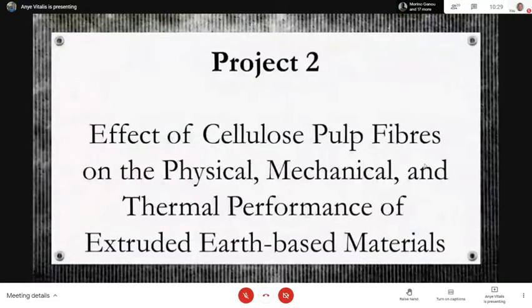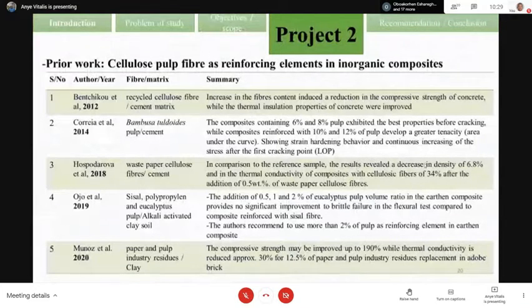Project 2 consists of the effect of cellulose pulp fiber on the physical, mechanical, and thermal performance of earth-based material. So now, what previous work has been done using earth-based material? We have Bentchikou et al. who studied recycled cellulose fiber in cement material, and realized that by introducing cellulose fiber, there is a reduction of the compressive strength and an improvement of the thermal insulation of the cement mortar.